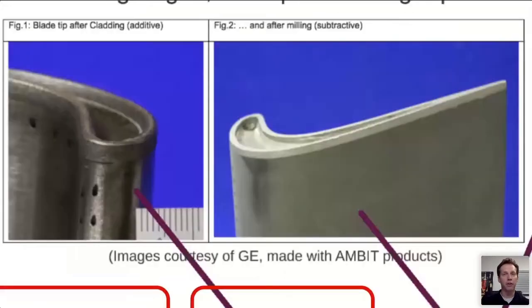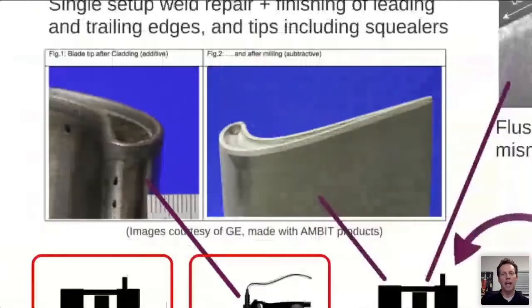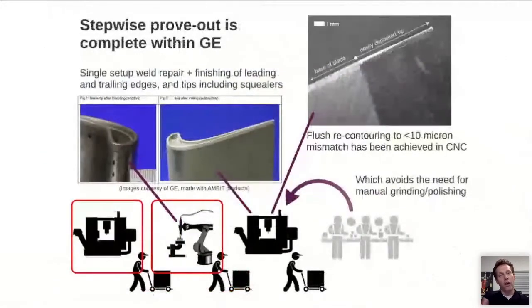Here's an example of a couple of steps that were done. So again, these images are courtesy of GE, but on the left, you see a squealer tip repair. This kind of top thing that looks like a Nike swoosh is one of the features on blades that some manufacturers use. And so on the left, it's as deposited. You can see it's gray and a little bit rough. On the right is after milling. And so this was proved out in a sequential sequence and then followed on by other types of repairs as well. And I'll zoom in here.